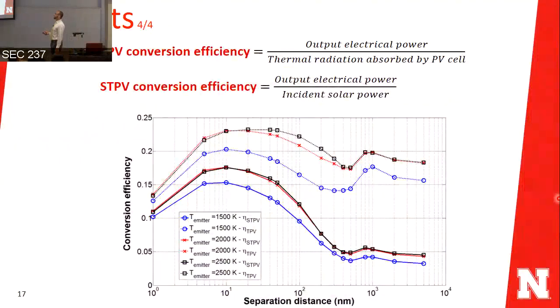The last piece of results is the efficiency of the system. I have two efficiencies here: the thermophotovoltaic efficiency, which is the efficiency of the absorber emitter and the PV cell, and the efficiency of the total system. The efficiency of the thermophotovoltaic is in dotted lines, and the efficiency of the total system in solid lines. You notice that the total system has a low efficiency at far field, when separation distance is higher. And why is this? Because near field thermal radiation has not taken part yet. Once near field thermal radiation takes part, the efficiency jumps high.